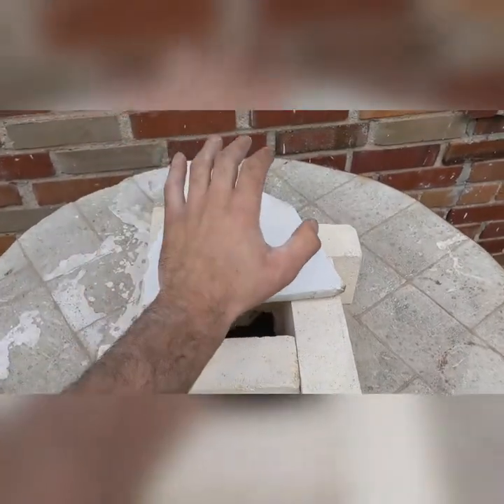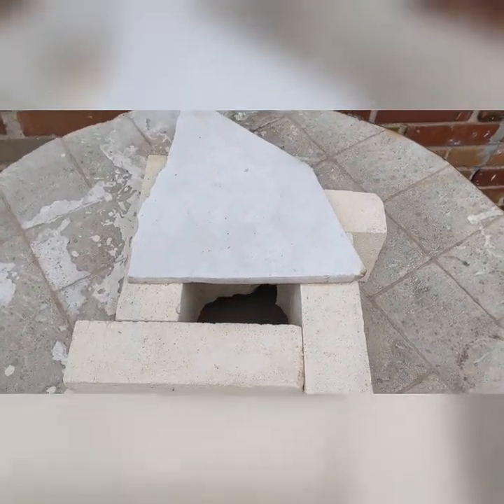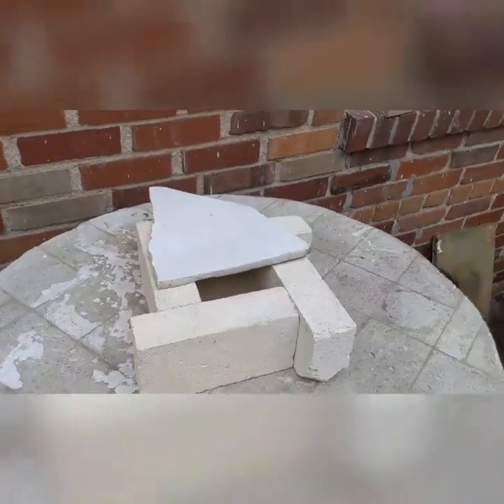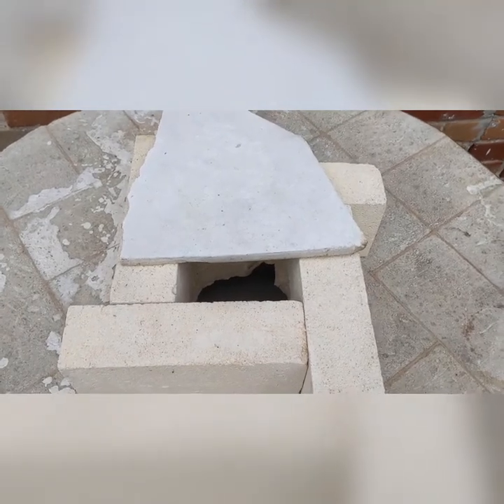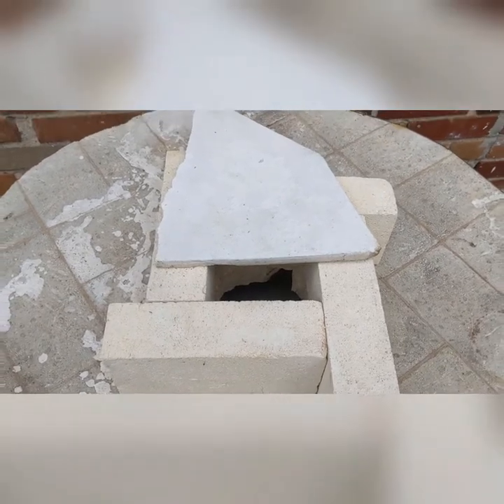So it's about three and a half hours after I started the kiln. As you can see, the kiln does not quite have any glowing red color yet, but we are nearing quartz inversion. I can tell that by the roar of the burners, and also looking inside the burner ports, the bag wall bricks are starting to glow just a little bit. Normally I would turn up the kiln at this point, but I'm actually going to leave it and let it slowly climb through the 900 to 1200 degree range at this gas setting, and then turn it up right after that.